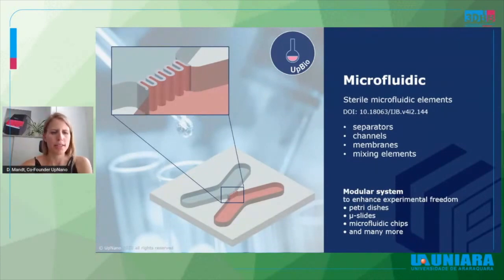And when doing customized microfluidic chips like this, you can see here, this is a model from my master's thesis. The outer microfluidic chip, so this X shape, was cast with PEGDMA, and then the membrane you can see in the detail image at the top was printed with the 2PP setup. This membrane is a semi-permeable membrane printed with the biomaterial. By choosing the hatch and the layer and line distances, you can also influence, for example, the porosity or the permeability of this membrane. In this case, it was meant to be a placental model.